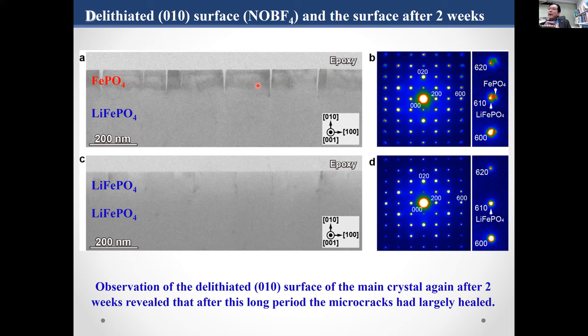But if the particle size is small, like 100 nanometers or so, even delithiated, the strain itself is not so large and the crack will not occur. I think this phenomenon depends on the size of the particle. Looking at this crack formation, semi-periodic, it looks like 200 nanometers. If it's below 200 nanometers, maybe it's harder for cracks to form. And this crack formation is all parallel there, yes.